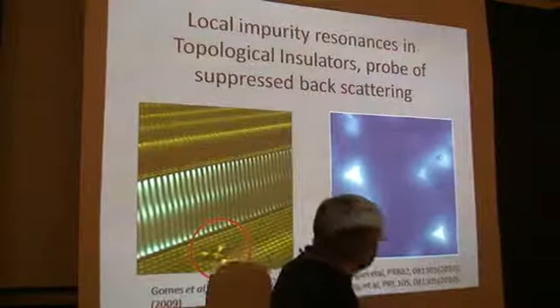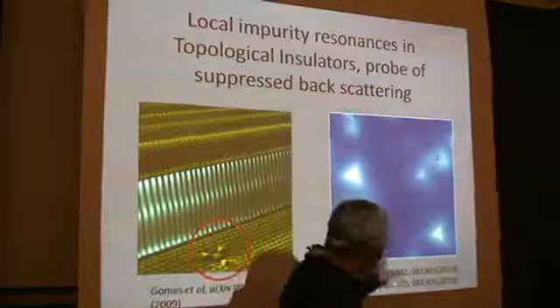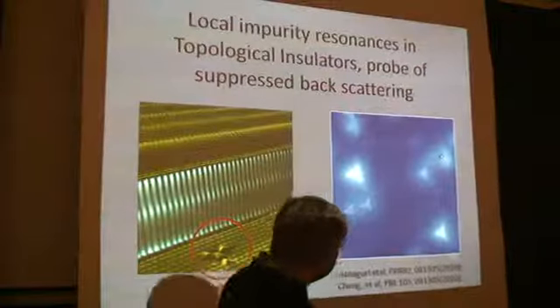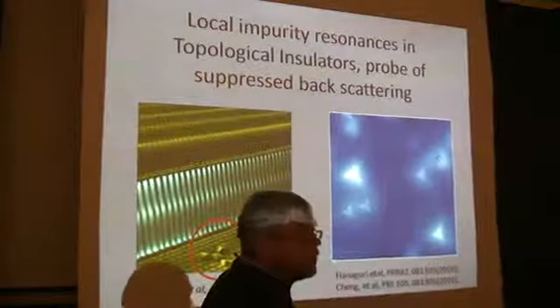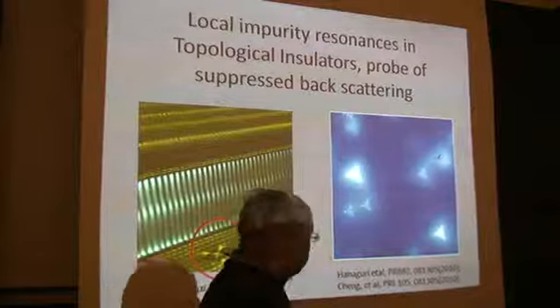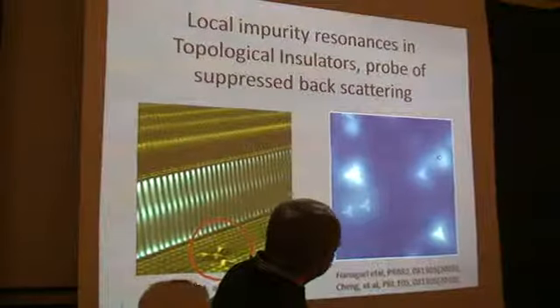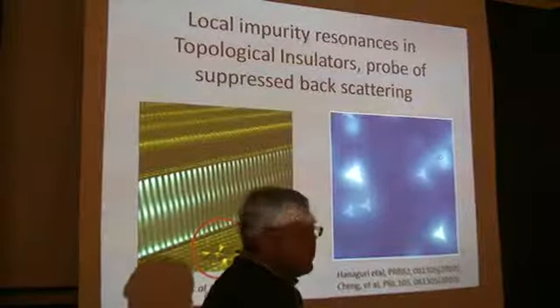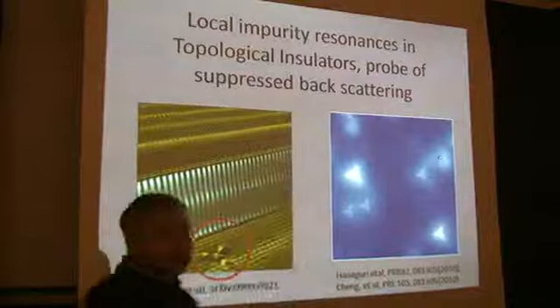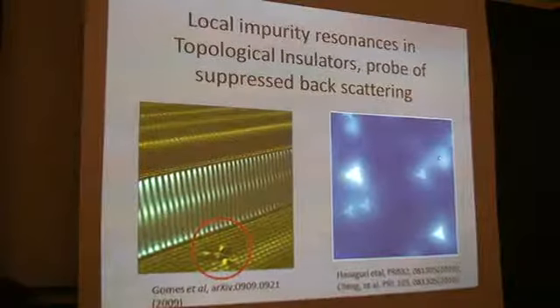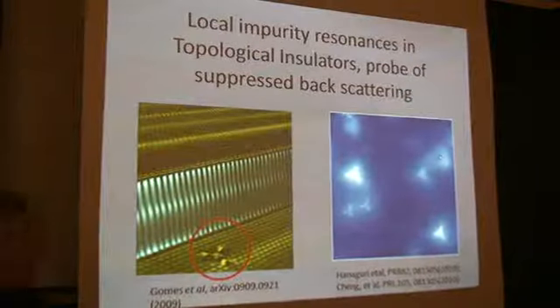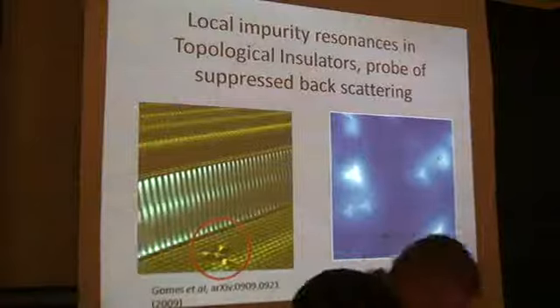You can see that in the given field of view, this mesh is about atomic distance, so this would probably be maybe 50 angstroms, maybe 100 angstroms. What you see is quite a few defects coming in. And so these materials are quite a bit disordered. Maybe not in the sense of the total conductance, but locally there are some defects. You can see them.